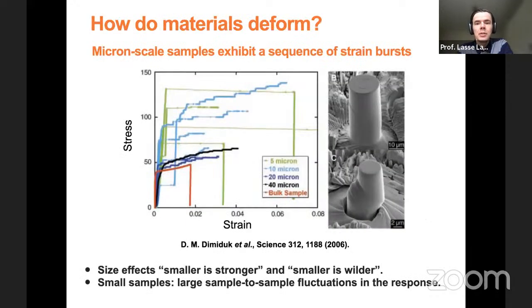Okay, so the key experimental background here is that you take these micropillars, which are pillars of some metal that have a size in the micrometer range, like a few micrometers or maybe 10 micrometers. And then you compress these with a nano indenter. It's a small thing that you use to push and compress these pillars, and you can record the stress as a function of strain for samples of different sizes. What you will find out is that, especially in these small samples, you have fluctuations in the response. You have a staircase-like structure of your stress strain curve, which consists of strain bursts, which are the horizontal segments, and then some stress increments in between.